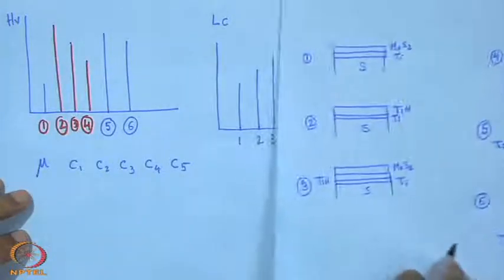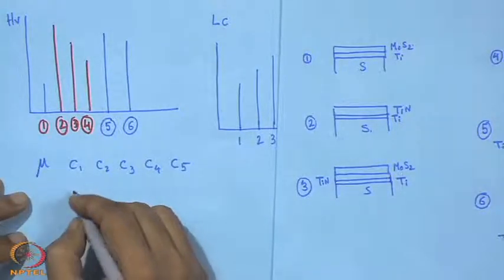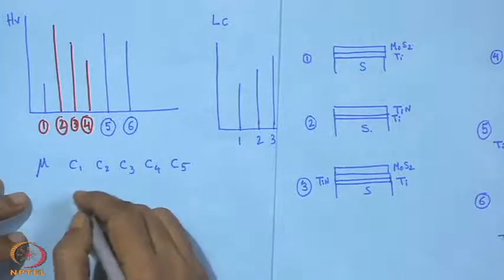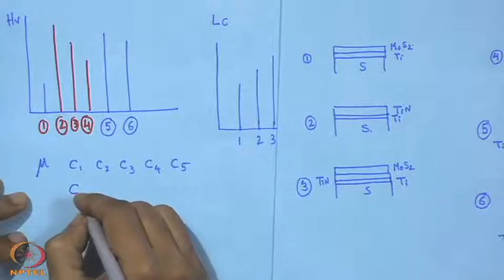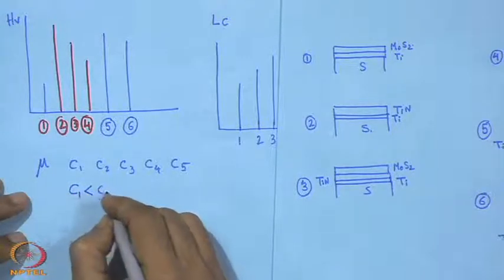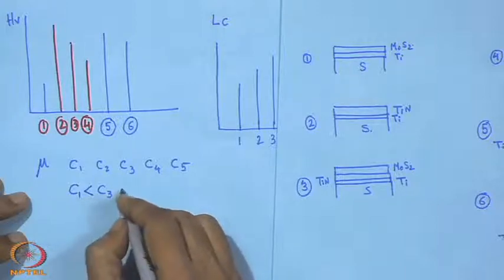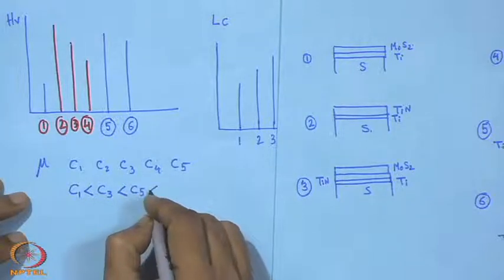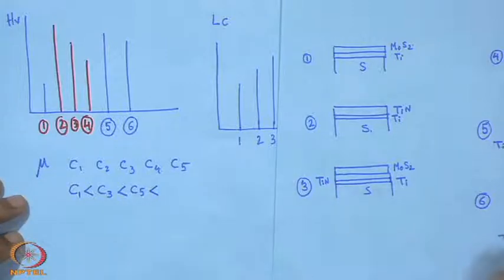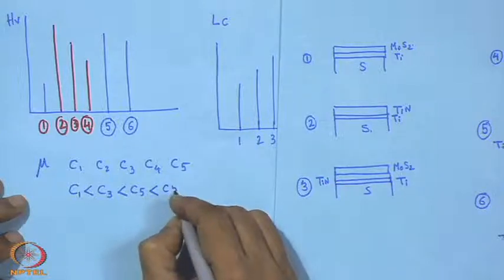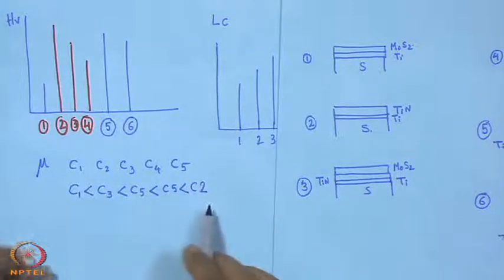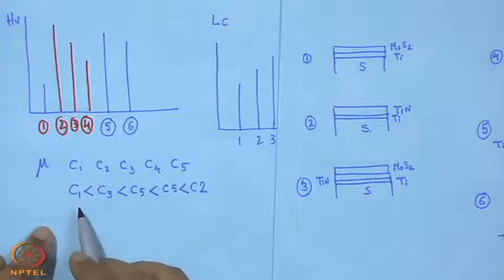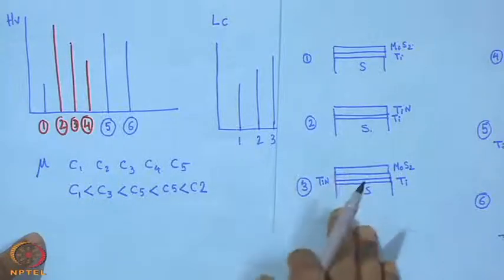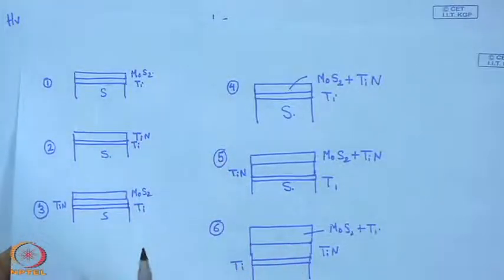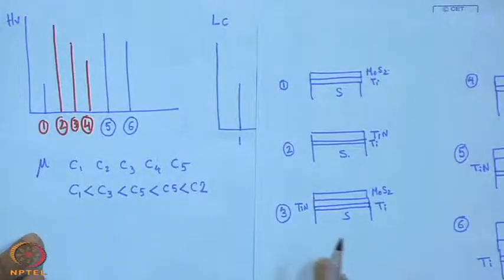So, what we can put in this case is that C 1 shows the lowest coefficient of friction, then we have C 3, that is the second lowest, followed by C 5, and finally C 2. So, in that scale, C 1 happens to be the one which gives the lowest value of coefficient of friction, because of this MoS2 and TiN,